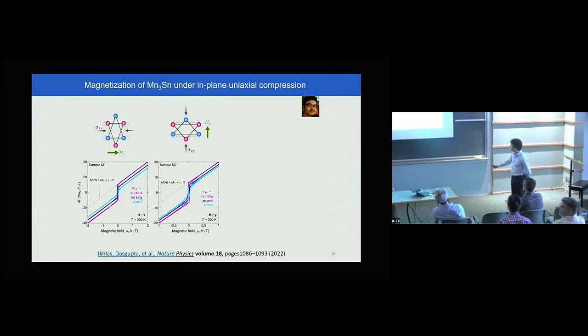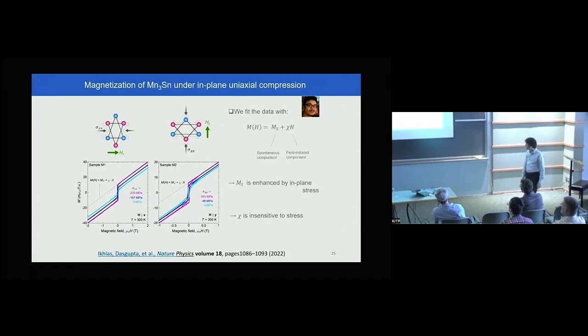So if you increase this uniaxial pressure, then systematically this magnetization goes up, okay? And the field dependence stays nearly the same. So there are two components of the magnetization: spontaneous part and also field-induced part. And this spontaneous part is actually enhanced by in-plane stress. And the field-induced part is somehow independent. And susceptibility is nearly constant.